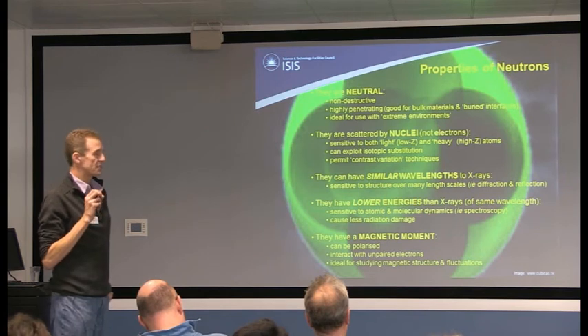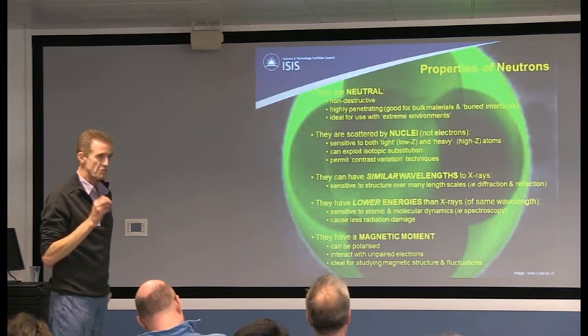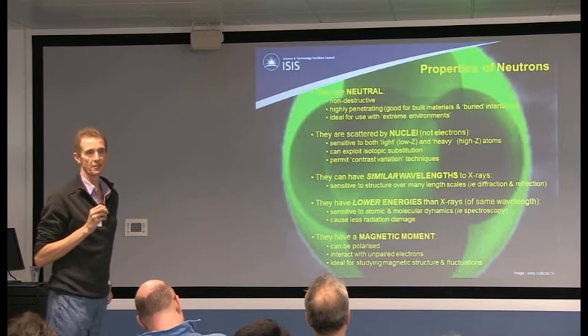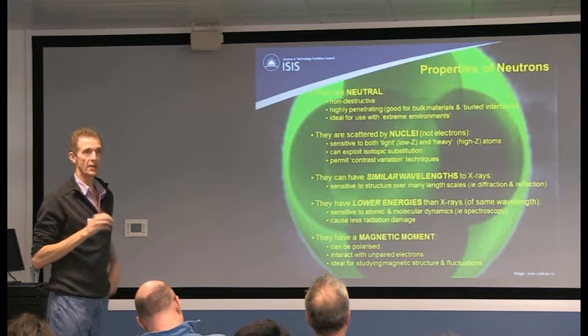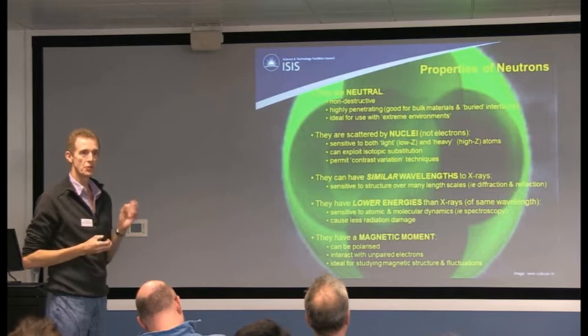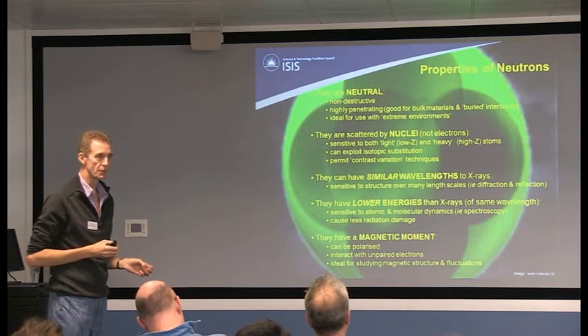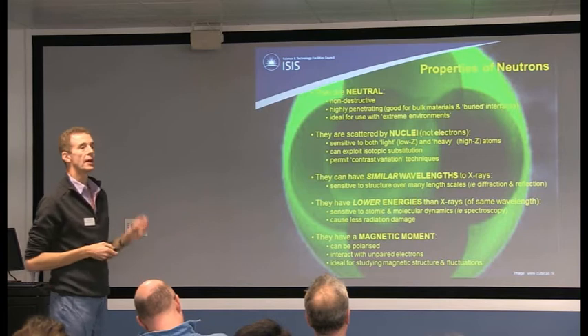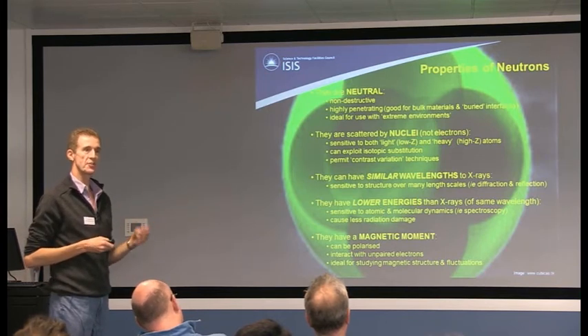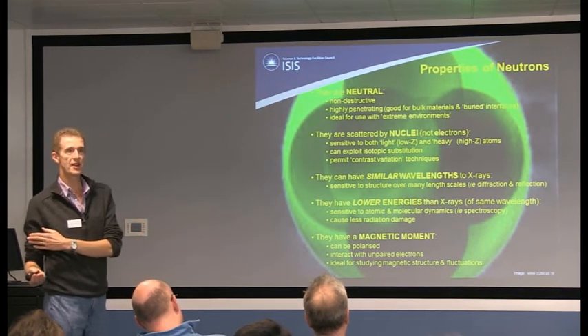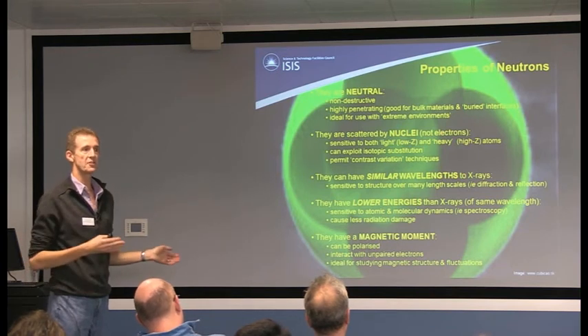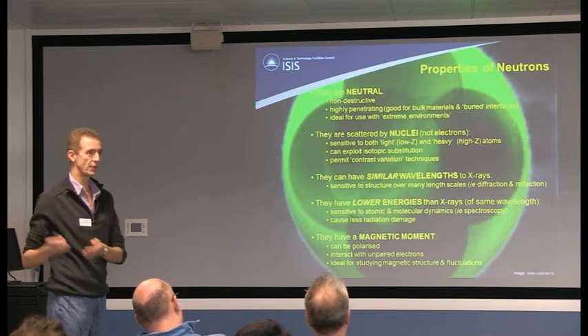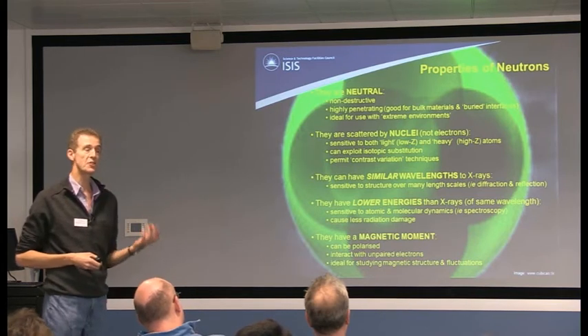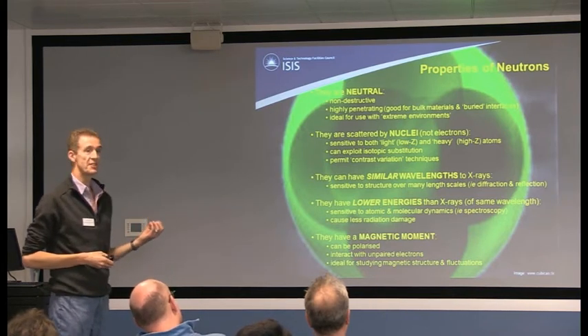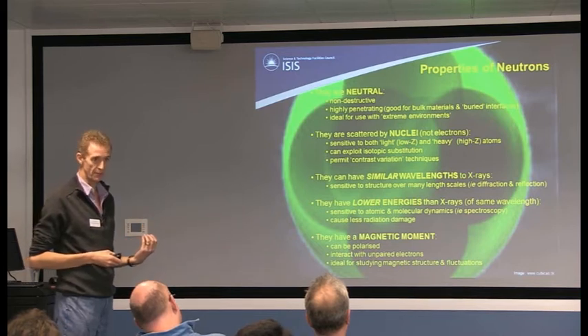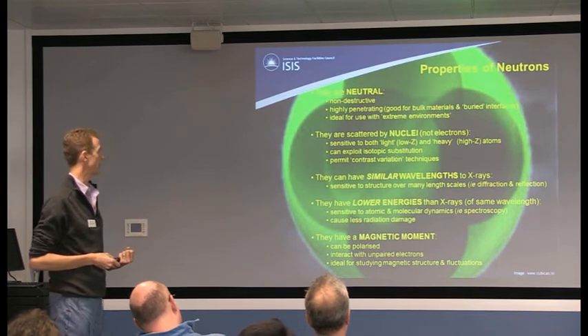The reason that neutrons and X-rays are complementary is in the mechanism by which the neutrons are scattered. Light and X-rays are scattered by the electron clouds around atoms, but neutrons are scattered by the nuclei themselves - fundamentally different. That actually means we are sensitive to the light elements as well as the heavy elements, whereas in X-ray scattering it tends to be the heavy elements that dominate your scattering. It also means that neutrons are sensitive to different isotopes of the same element, which X-rays are not.